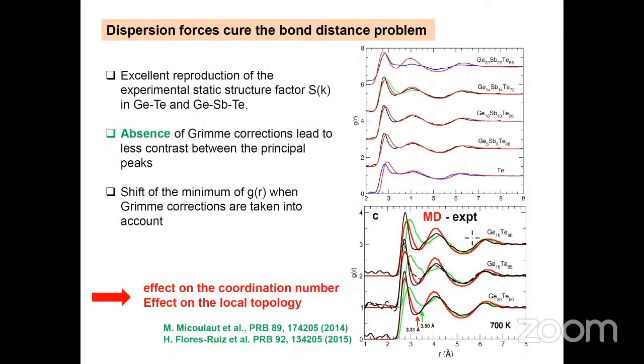So we have found for a variety of systems in the amorphous phase, but also in the liquid phase, that the inclusion of those dispersion corrections corrects very nicely the structure functions, in terms of the structure factor or the pair correlation function. This is the comparison between theory-calculated structures and measured ones. For example, here you see different ternaries in the GST liquid, where the red curve, which is a calculated one, compares very well with the black one, which is the experiment from neutron diffraction. These are results from other groups, the blue curves, so I won't comment on that.